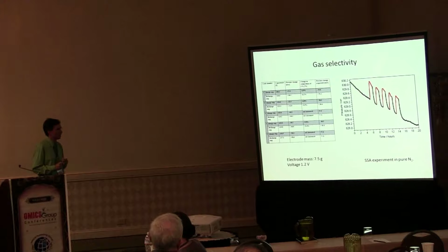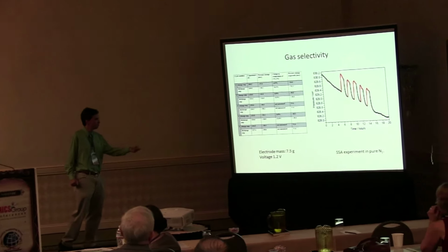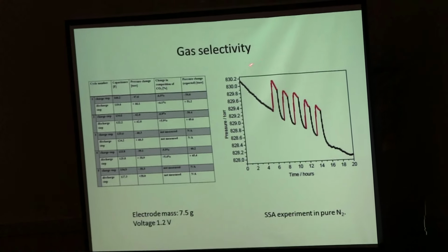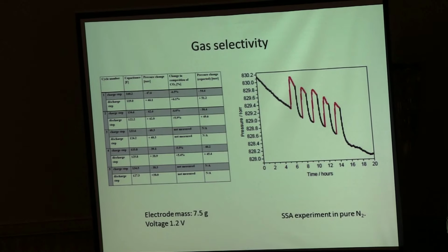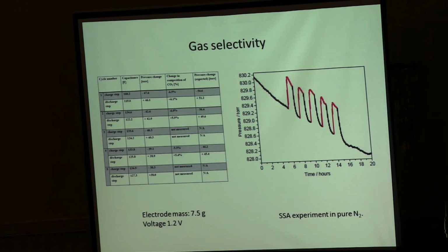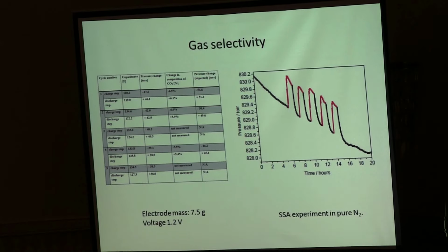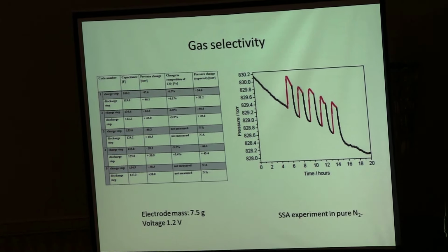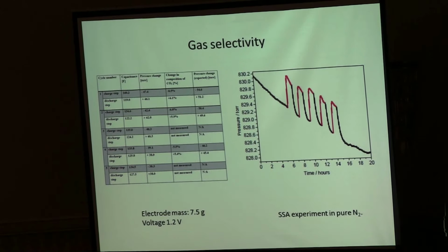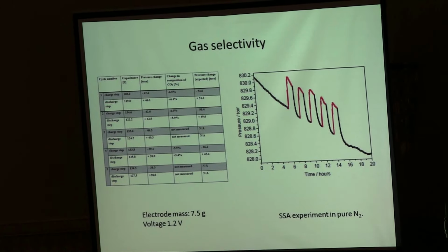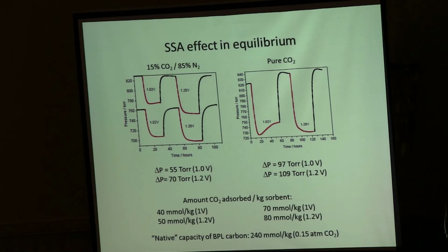In addition to that, we did a control experiment in pure nitrogen, and we found that in pure nitrogen we even see a slight, even though very small, pressure increase as we charge. That means that N2 may be repelled from the electrodes when we charge, while CO2 is attracted.